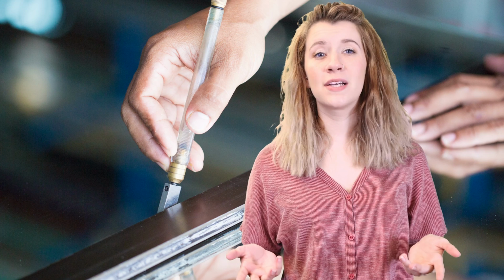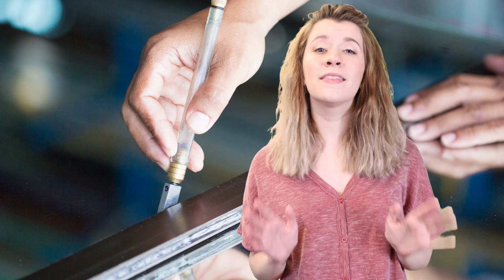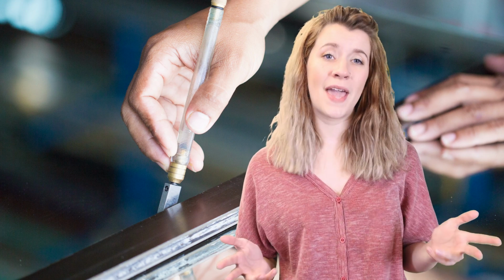Cutting glass after this process is possible, but it'll weaken the glass around the area where the cut was made. Chemical strengthening can also be done on thinner glass, where tempered glass needs a thicker cut due to the internal stress being put on the glass. When you temper a 3 millimeter thick mirror, it is super warped and still breaks quite easily. Depending on the shape, it can also be bendy, which is so weird to me. That is why we typically do not supply tempered mirrors at 3 millimeter thickness or thinner.